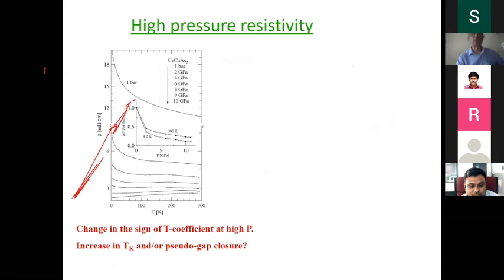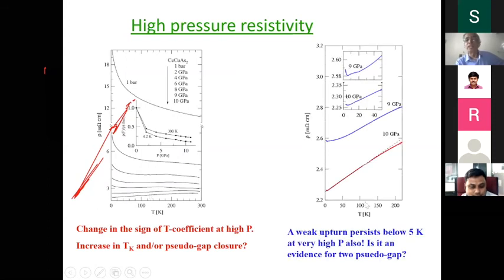Okay, so for the same material, when we applied pressure, you could see there's a change in the temperature coefficient. This is at zero pressure, or no external pressure. Under pressure, there's a change in the feature. Here, it completely becomes a positive temperature coefficient. You can go from this region to that region under pressure, and also go through a very interesting intermediate feature, linear behavior of resistivity. In this region, you could see quadratic. Here you see a linear behavior. It's a non-Fermi liquid behavior again.